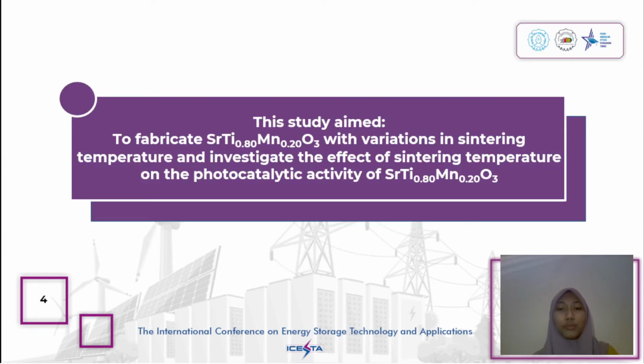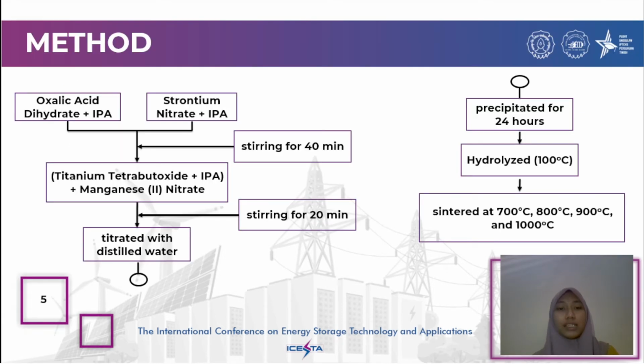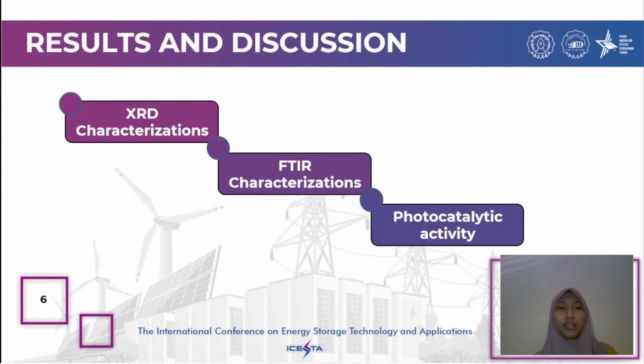This study aimed to fabricate strontium titanate doping mangan with variation in sintering temperature and investigate the effect of sintering temperature on the photocatalytic activity of strontium titanate doping mangan. The following is the preparation of strontium titanate doping mangan materials. And then the sample is characterized using XRD, FTIR, and photocatalytic activity by UV spectrophotometer.